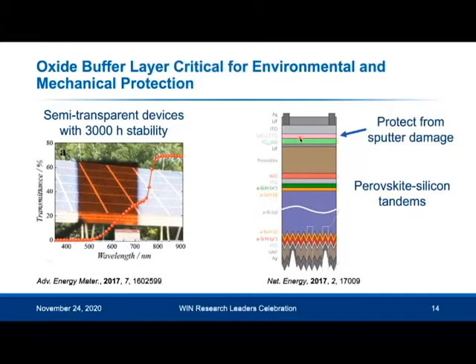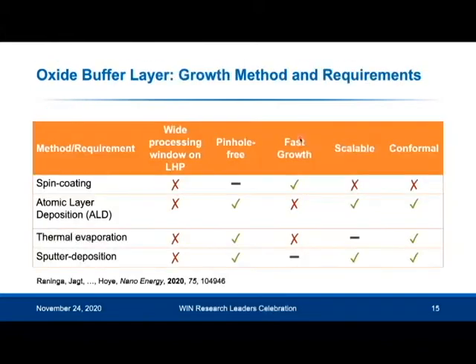And this oxide layer doesn't need to be very thick. 10 nanometers has been found to be sufficient. And currently, the methods for growing this oxide layer include spin coating some oxide nanoparticles. They include atomic layer deposition. You can also thermally evaporate some oxides, and some people do use sputter deposition, but this is not very commonly used because, as I mentioned, sputter deposition is a very high energy process.